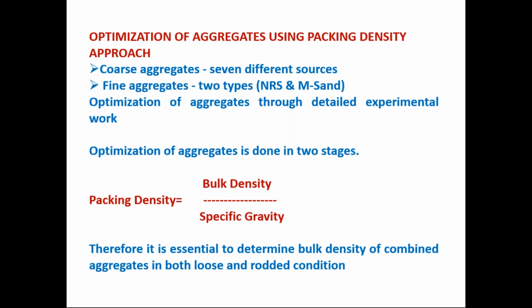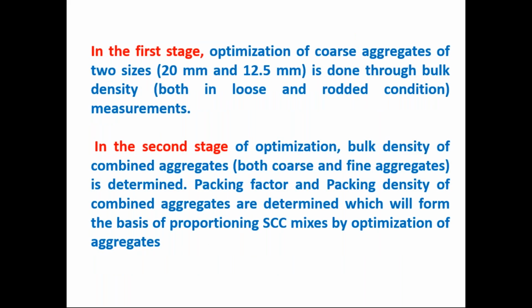So we can optimize the aggregates by finding out the packing density, which is defined as bulk density divided by specific gravity. So it is essential to determine the bulk density of combined aggregates. We need to find out the combined bulk density, not the bulk density of coarse aggregate and fine aggregate alone. We need to find out both in loose state as well as in rodded condition. If you want to really achieve a good packing density of aggregates, first is optimization of coarse aggregate of two sizes, because we don't get any mixed aggregates. We always get single size aggregate from the crusher, so we blend them and optimize them through the bulk density method.